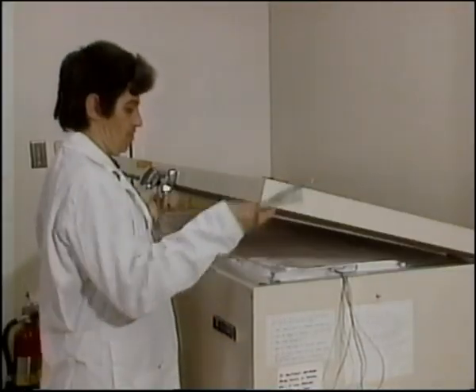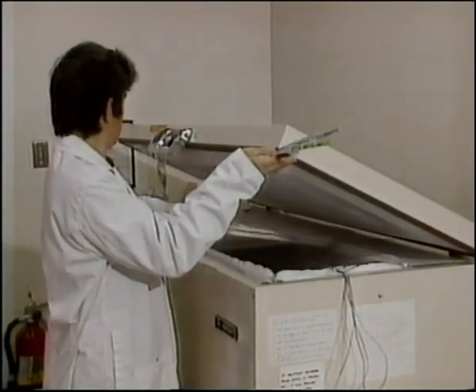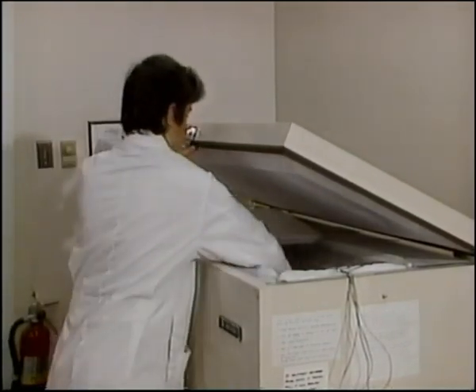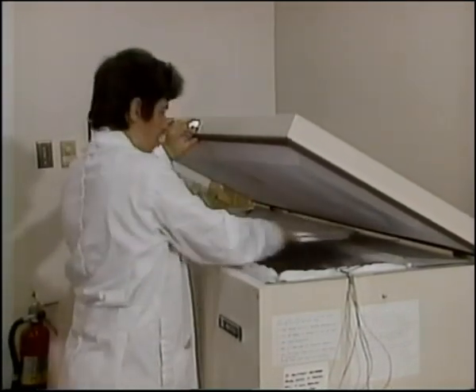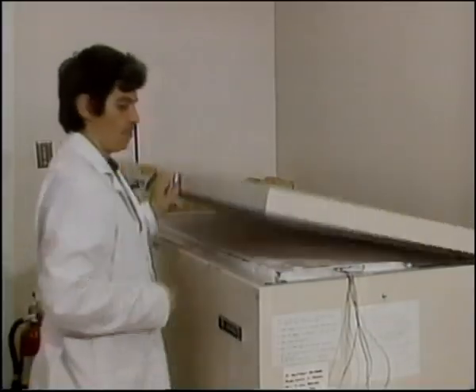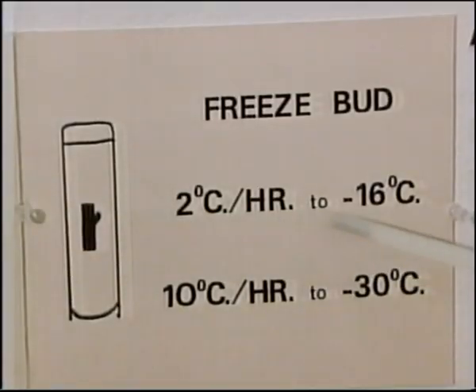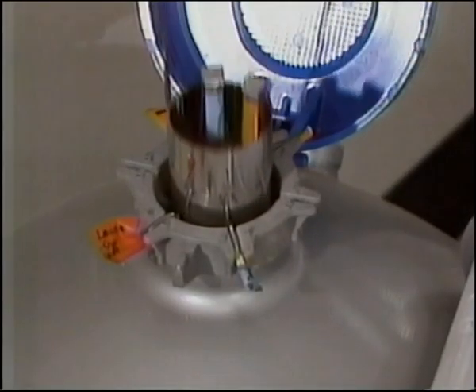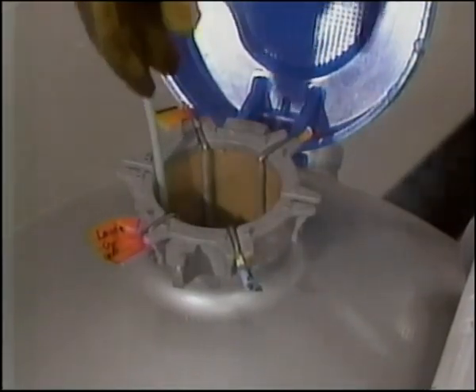The third step, then, is to freeze the bud at a specific temperature program. We begin the freezing process at 2 degrees per hour to -16, and then at 10 degrees per hour to -30. The buds are held at -30 overnight, and from that point are plunged into liquid nitrogen at -196.